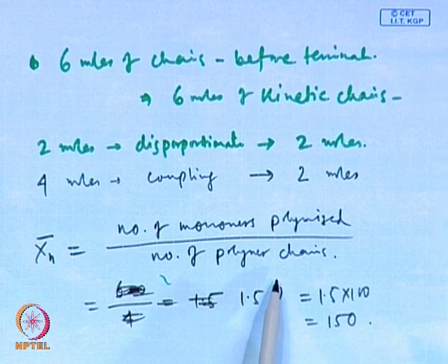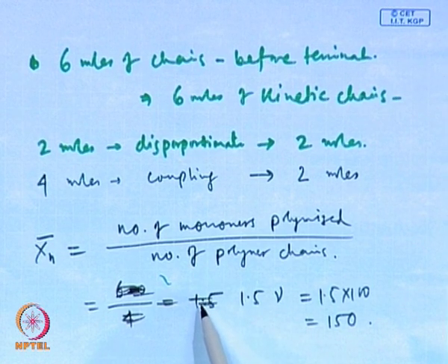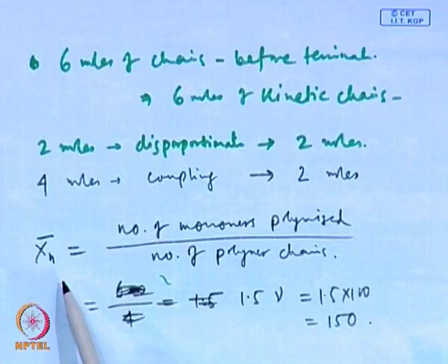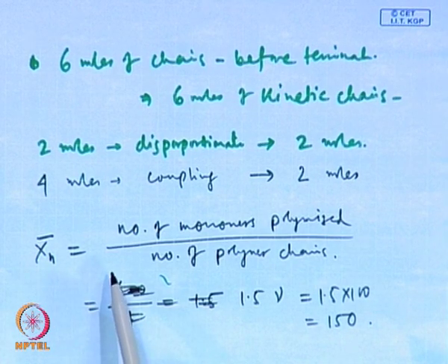So, when you talk about the polymer distribution, it contains monomer, dimer and trimer as well. In case we find in a step polymerization that our polydispersity is less than 2 in spite of having a high molecular weight, what could be the reason? We have found that in step polymerization the theoretical polydispersity is always 2 if we get a high enough molecular weight, because it is given by 1 plus p, and p should be almost 1 to get a high molecular weight.